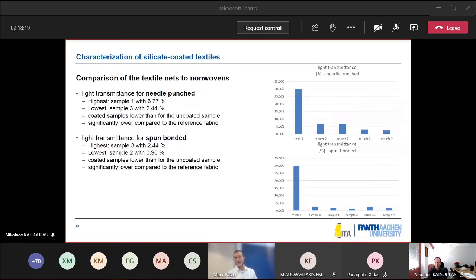For the light transmittance, as you can see on this slide, the highest light transmittance we reach with sample one for needle punched and sample three for spun bonded. And the lowest was sample 3 for needle punched and sample 2 for spun bonded. All in all, I can say that for needle punched and for spun bonded, the coated samples have a lower transmittance than the uncoated samples, and the light transmittance is significantly lower compared to the reference fabric.